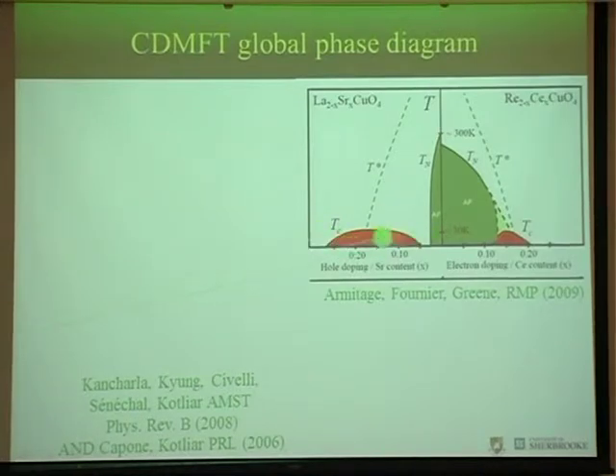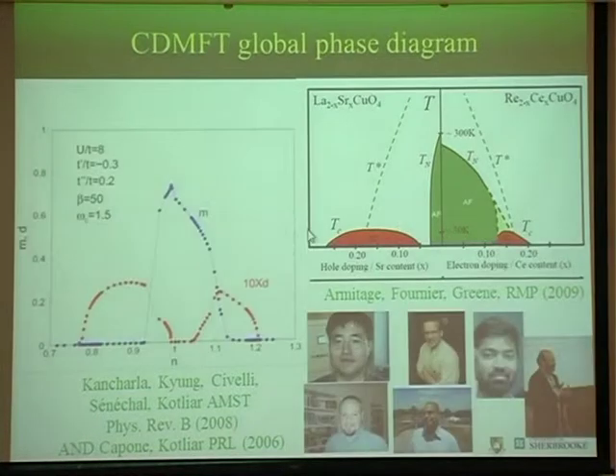So this is, again, the experimental phase diagram of the high-temperature superconductors. I didn't talk about the charge density waves in this one, but now the filling goes from left to right. So the electron doped are on the right, and the hole doped are on the left. So the cellular dynamical mean field theory phase diagram at 0 temperature looks like this. So in blue, the band parameters are taken from band structure calculation. And the antiferromagnetic order parameter